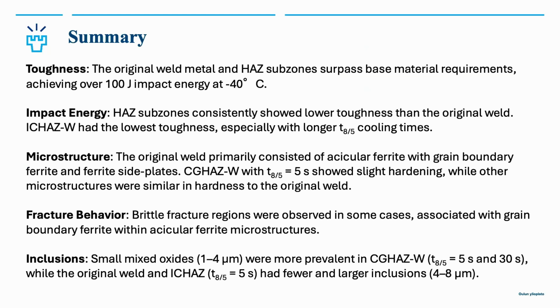Oh, yeah, in the summary already. So regarding toughness, it was seen that the requirements are surpassed easily in all cases. And when we see the impact energy, it was seen that it decreased in heat affected zones compared to the original weld, and especially in the intercritical heat affected zone with longer cooling time. And the microstructure was primarily acicular ferrite, but there were grain boundary ferrite and ferrite side plates too.